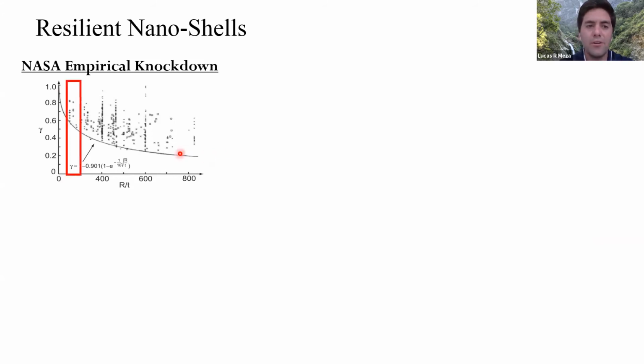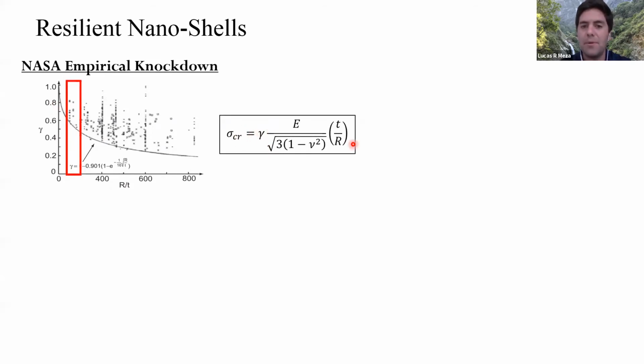Our structures were in a relatively low aspect ratio regime, so that shell buckling formula I had before, E over square root of T over R, there's actually a gamma out front that I conveniently ignored. This knockdown, this gamma, can drastically decrease your properties when making very thin shells. You get about a factor of 5 decrease in load carrying capacity over what it theoretically can carry, meaning shells are highly sensitive to imperfections. So if you want an ultra lightweight structure, you run into this problem very quickly because shells aren't optimal.